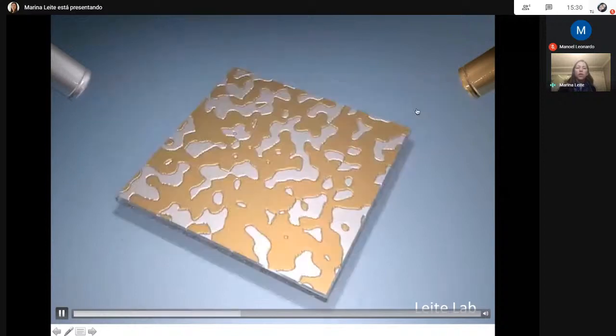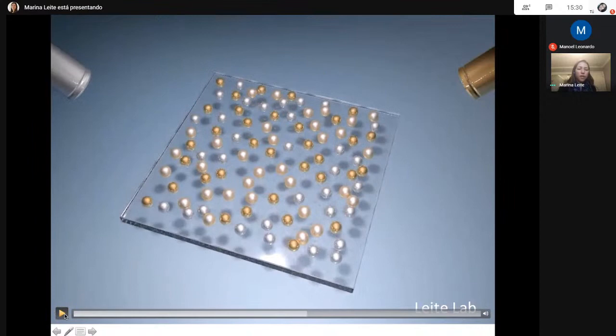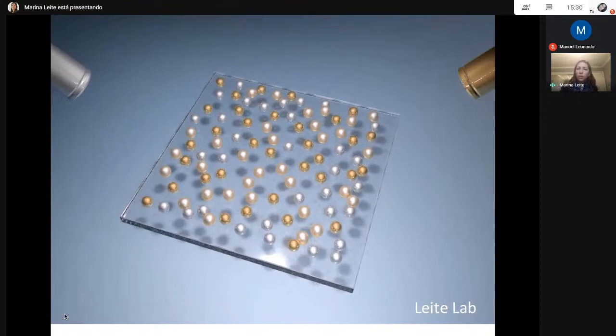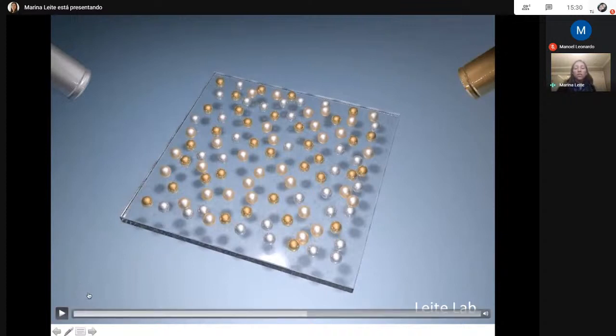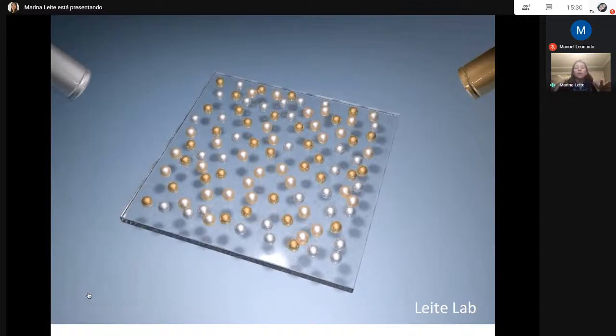We rotate the substrate. And then after that, we do an annealing treatment at a very well controlled temperature and in a very well controlled environment. Depending on the metals that we have, the substrate, in this case glass, and the temperature and time of the annealing, we can promote what we call surface dewetting. Dewetting, from the Portuguese molhar, right? To minimize Gibbs free energy, instead of having a thin film, the ultimate result is going to be lumps of nanostructure.